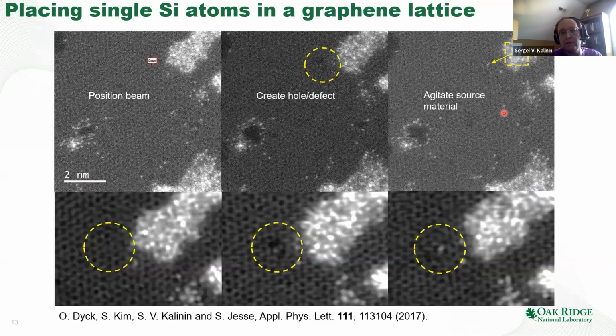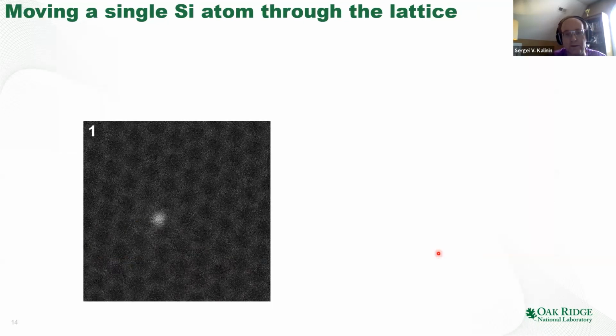That was interesting, but then we decided that rather than exploring the 3D, we really need to focus on being able to control atoms one at a time. To do that, we switched to two-dimensional materials. These are a few examples of how the process can go. Here you see the perfect graphene. Here we use the electron beam to create a hole, just vacancies. Now we have agitated this contaminant on the surface, which contains silicon atoms. One silicon atom has diffused and dropped into the vacancy on the graphene surface. So it formed a silicon insertion. So we manipulated the silicon to make a dopant inside the graphene lattice.